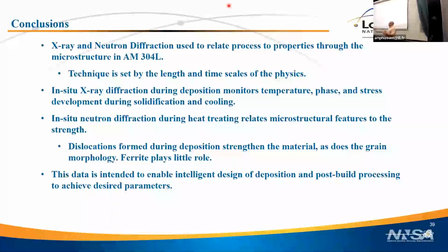When we do the mapping, we can certainly see the ferrite fraction, for instance, as a function of height within the deposit, right? So we can look at that wire and say there's a lot of ferrite on the top surface. And then when we put the second layer on it, we can see that ferrite disappears, but then there'd be ferrite on the top of the second surface. So we can see heterogeneities on a line-by-line basis, but certainly not on a grain-by-grain basis. These measurements weren't done with that. I am 90% a powder diffraction person and 10% trying to do grain mapping type stuff.